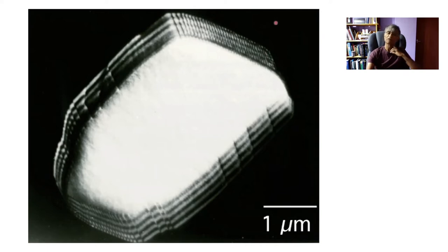And you can see these periodic arrays of dislocations in the interface between this precipitate and the matrix. But notice that when the orientation of the interface plane changes, we are not changing the relative orientations of the precipitate and matrix. But when the orientation of the interface plane changes, the periodicity of the dislocation structure also changes, and even maybe the Burgers vectors of those dislocations might be different.